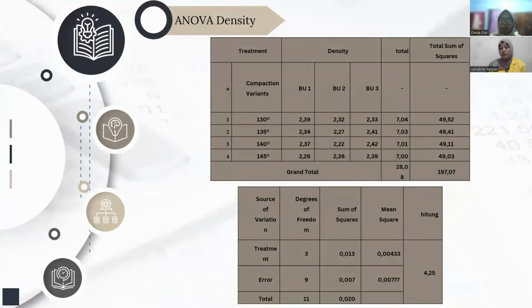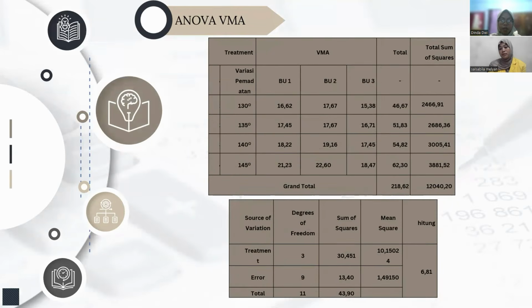Next, let's look at density. Density represents the compactness of the asphalt mixture, as you can see in this table. Temperature significantly affects mixture density, F value 4.25. VMA represents the voids between aggregate particles in the compacted mixture. Voids in aggregate show an effect with an F value of 6.81 as temperature increases voids space.